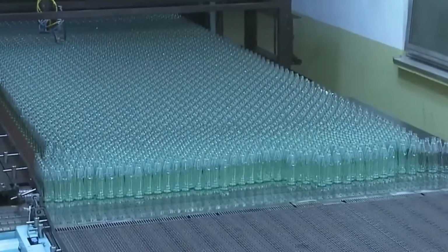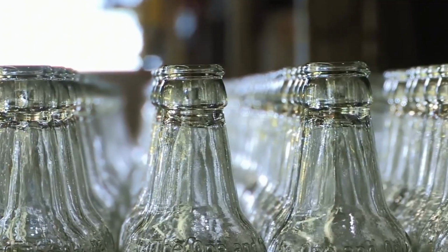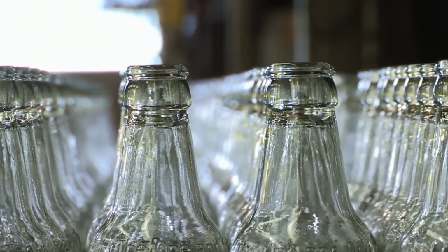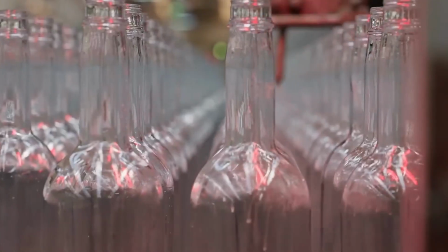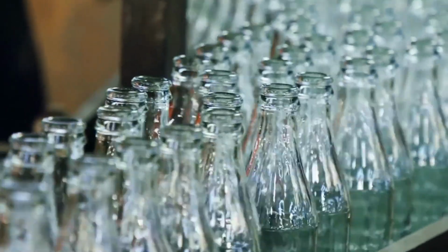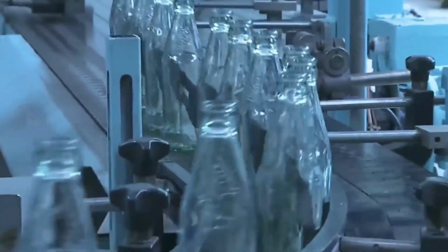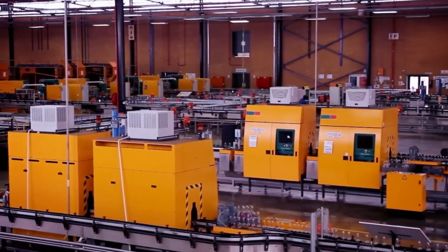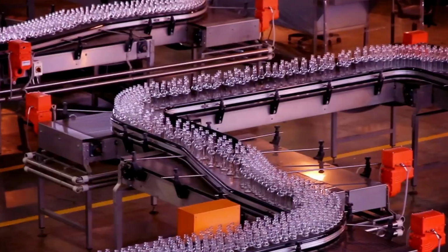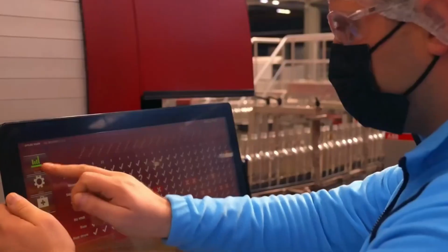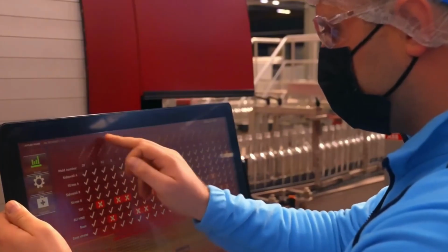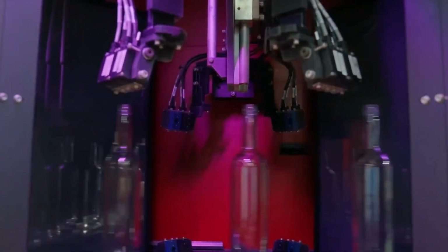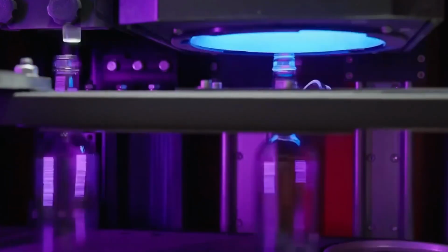And here's the insane part. At the exit, high-speed cameras inspect every bottle at over 1,000 per minute. Cracks, bubbles, or dimensional errors trigger automatic rejection. Rejected bottles are crushed and fed back as cullet. The loop closes with near-zero material waste. 1,000 plus bottles per minute inspected. Cameras catch flaws human eyes would miss in days.